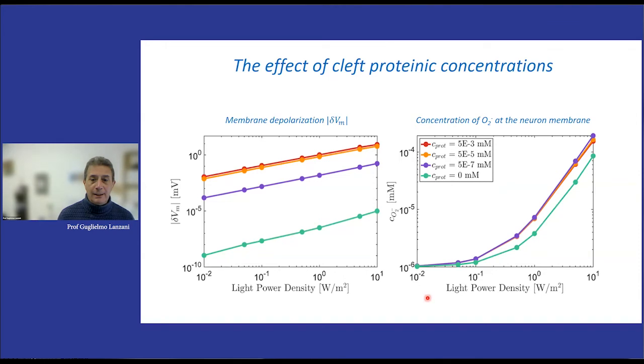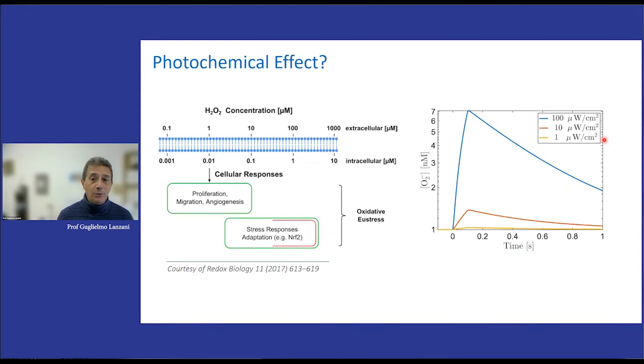The other thing you see here is that, of course, the proteins do not have much effect on the light intensity dependence and the concentration of, say, superoxide, which we consider can still diffuse in the cleft. The O2- however becomes important with the light intensity. And for the highest light intensity we are considering here, it is still below the nanomolar concentration. Now, we were considering the possibility that reactive oxygen species reach close to the membrane and can induce chemical interaction, affecting some ion channel that could be sensitive to this.